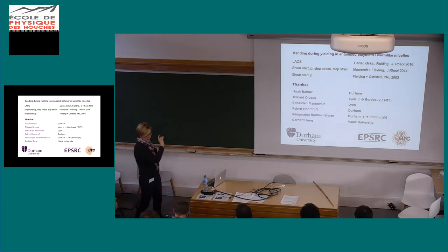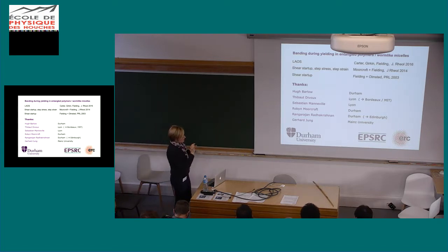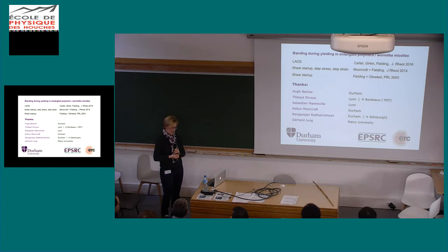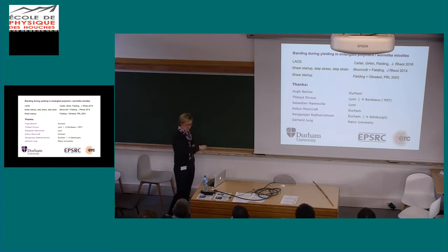The way space was put in the SGR model here, so what we did, we have a one-dimensional version and also a two-dimensional version. In both of those, we have stress propagators. So as you know, the SGR model has these plastic relaxation events, as in an elastoplastic model. And the original homogeneous version of the model didn't allow for coupling between those plastic events. In the 1D model, we do that by effectively integrating the Eshelby propagator over 1D. And in the 2D, we have an Eshelby propagator as in the elastoplastic models.